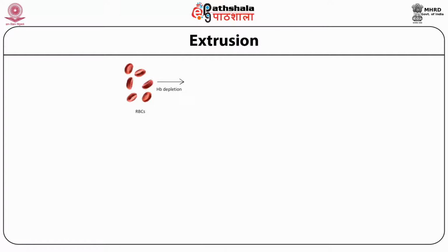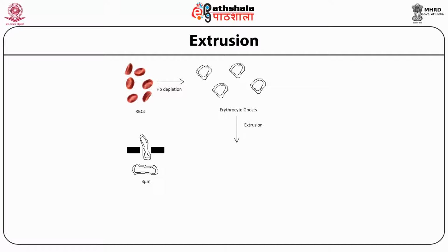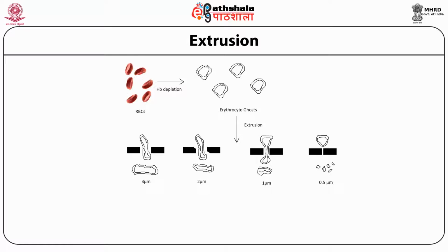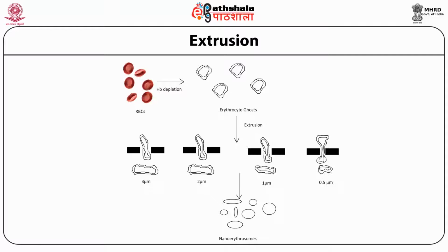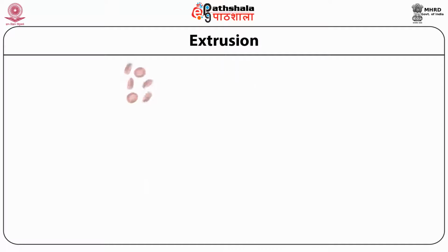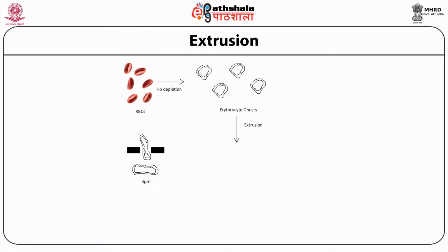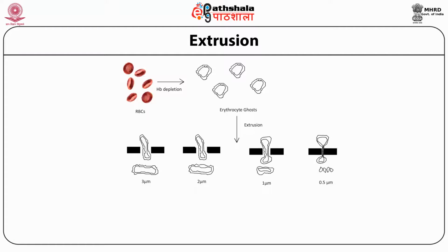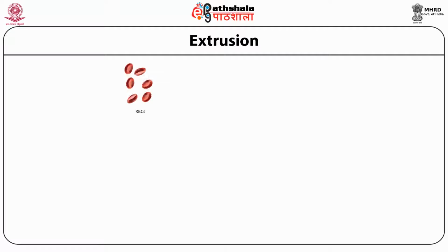Extrusion. The red cell's ghost dispersion of 50% hematocrit is passed across the 25 millimeter polycarbonate membrane filter of porosity 0.5 micrometer. The nanoerythrosomes are resulted by 8 to 10 sequential extrusions under the influence of nitrogen pressure. The nanoerythrosomes so resulted are tagged with uranyl acetate and they are visualized using a microscope. The extrusions are carried out in a thermostatically regulated extrusion system at 37 degrees Celsius, and the ultimate formulation is placed in a refrigerator at 4 degrees Celsius.